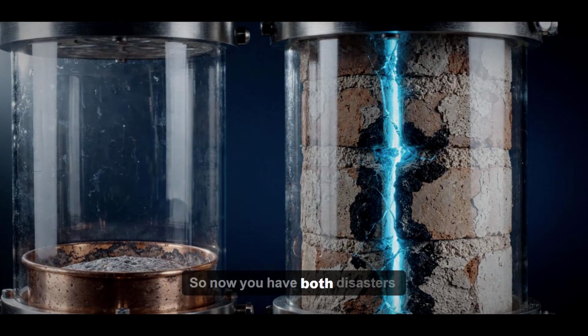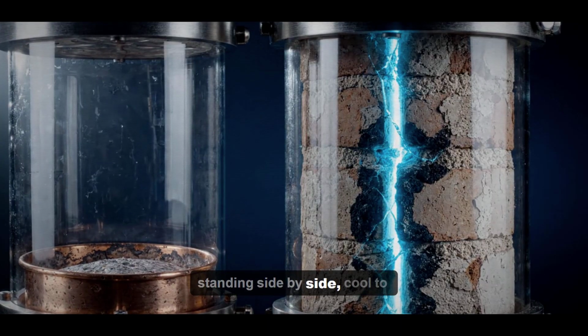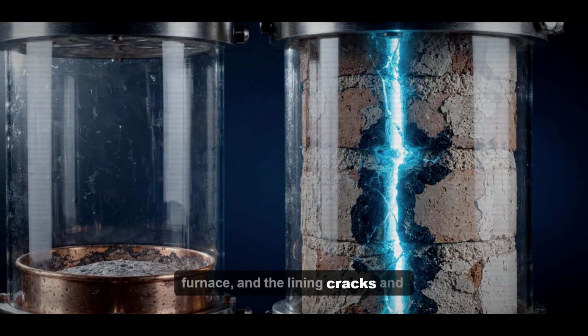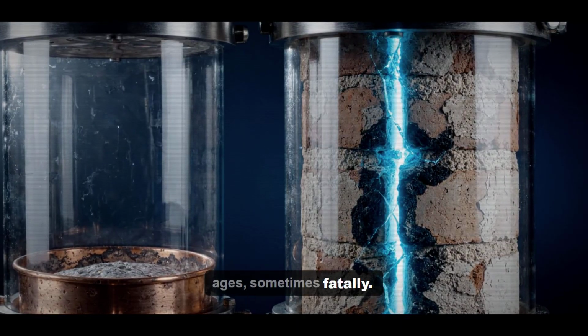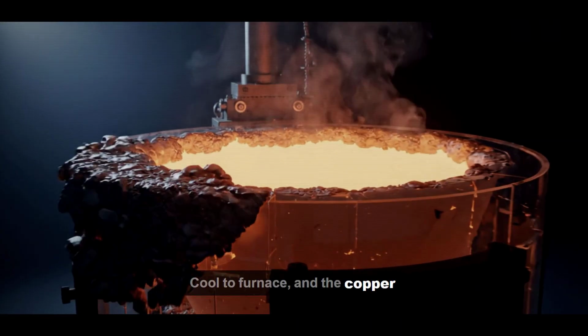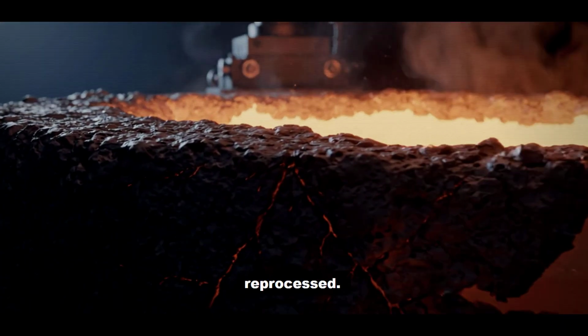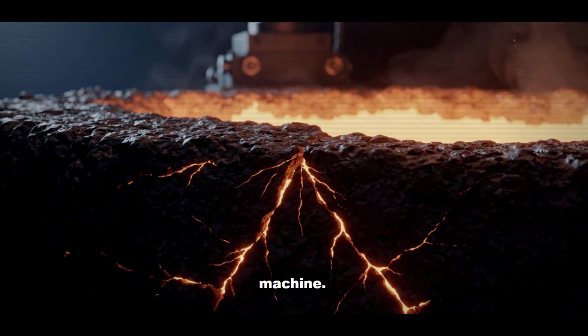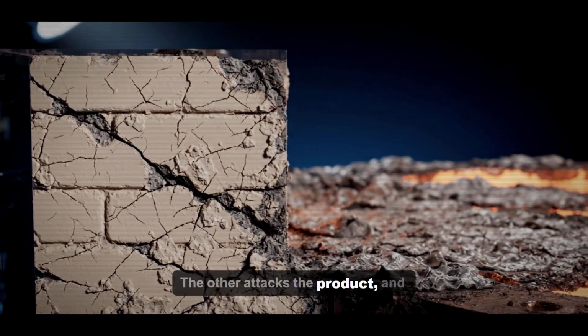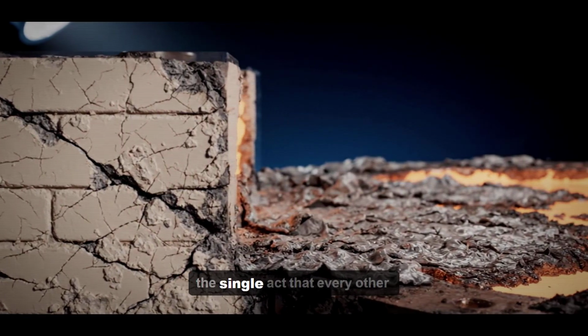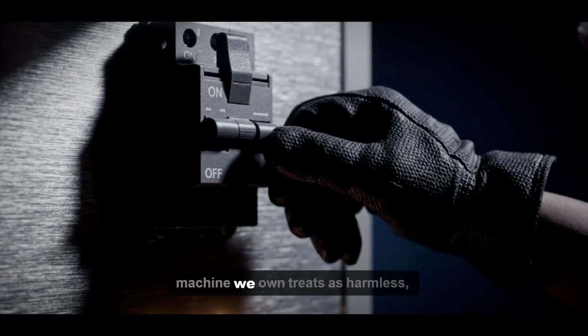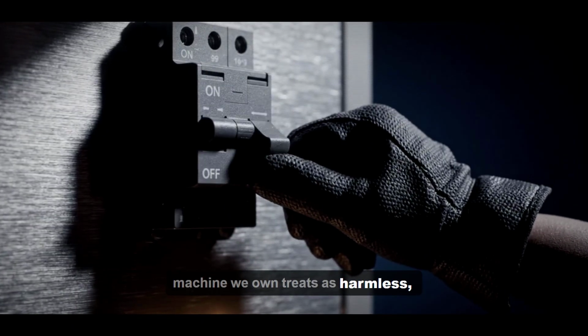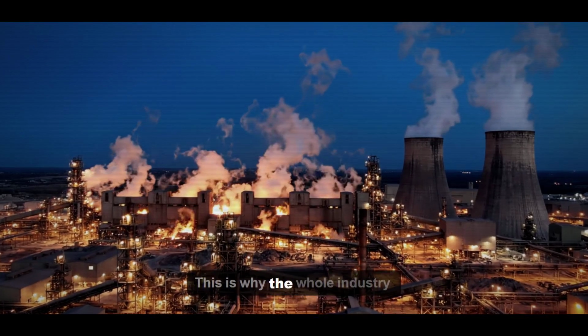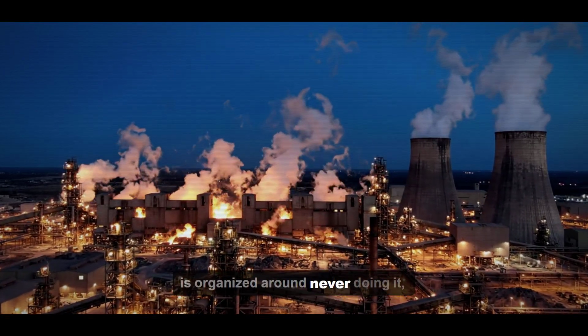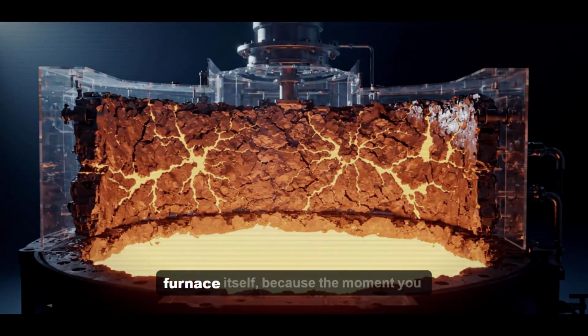So now you have both disasters standing side by side. Cool the furnace, and the lining cracks and ages, sometimes fatally. Cool the furnace, and the copper inside spoils and has to be reprocessed. One attacks the machine. The other attacks the product, and both of them are triggered by the single act that every other machine we own treats as harmless, turning it off. This is why the whole industry is organized around never doing it, and it goes further than the furnace itself,